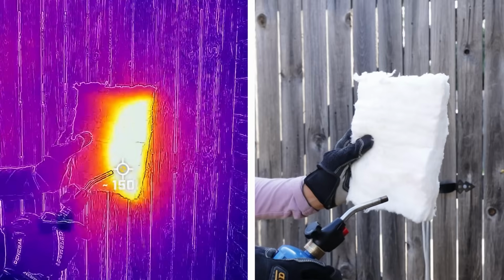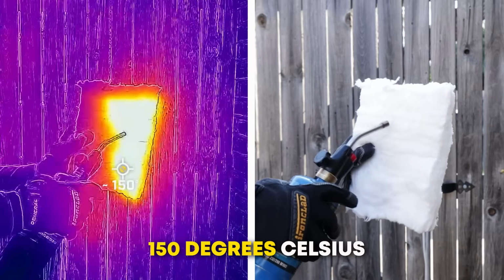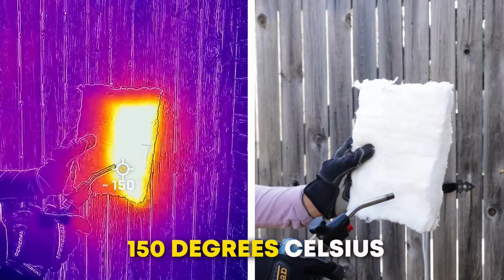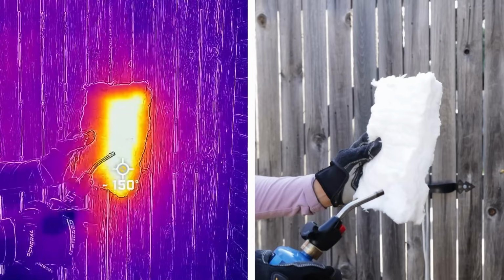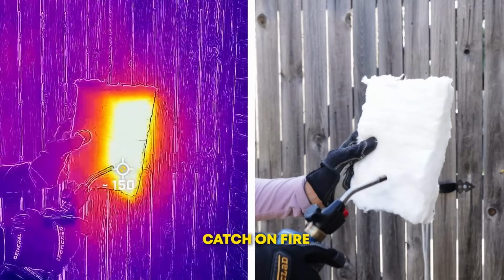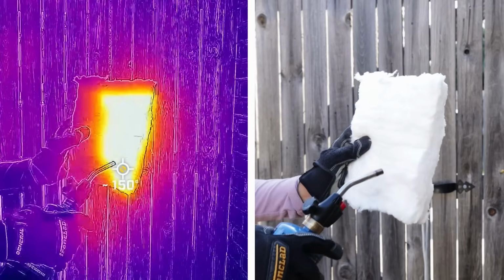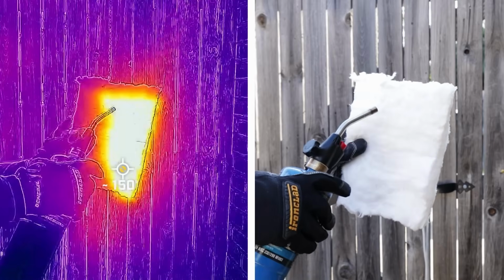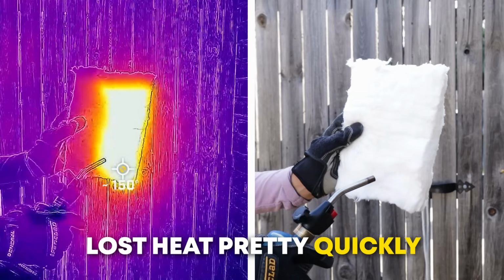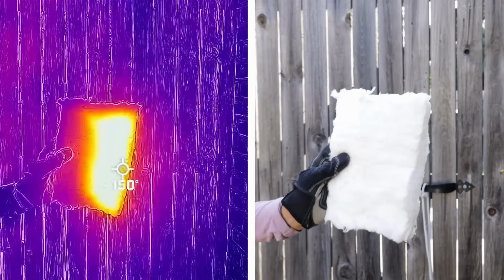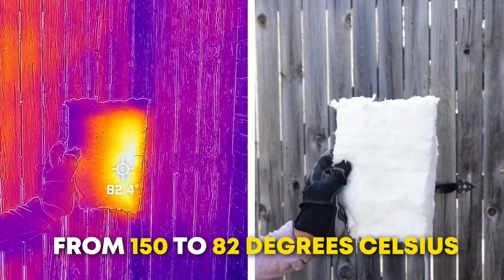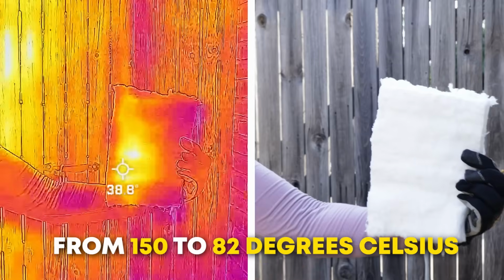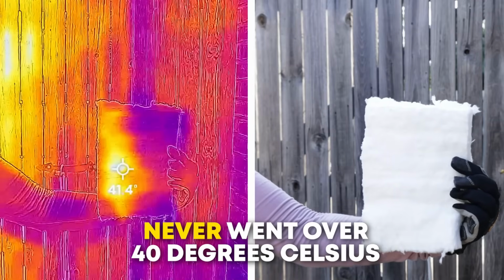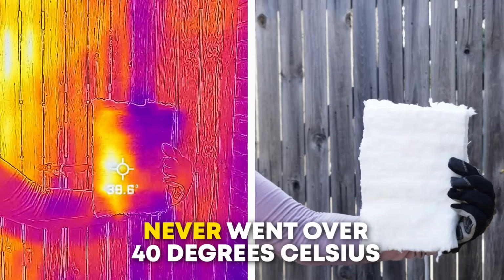Even though the temperature of the material rose to well over 150 degrees Celsius or 300 degrees Fahrenheit, it did not singe, smolder, or catch on fire. The back side of the blanket was actually cool to touch. It also lost heat pretty quickly after I turned the propane torch off. The front face went from 150 to 82 degrees Celsius, while the back face never went over 40 degrees Celsius.